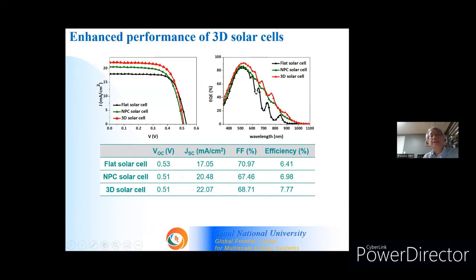And as you see, external quantum efficiency is increasing compared to the flat conventional solar cell, across a wide spectrum range. We believe this is due to the existence of multiple plasmonic resonances from our multi-petal three-dimensional nanostructures. The performance and efficiency are significantly enhanced compared to the flat solar cell.